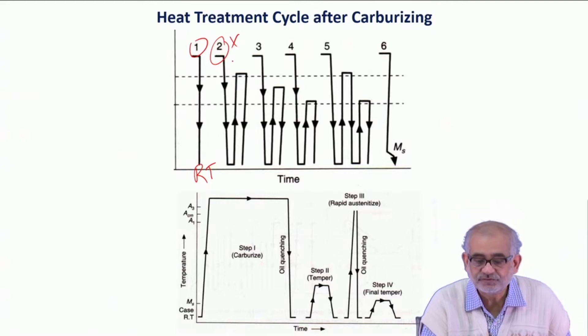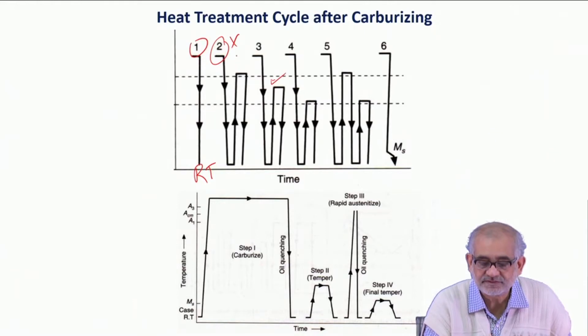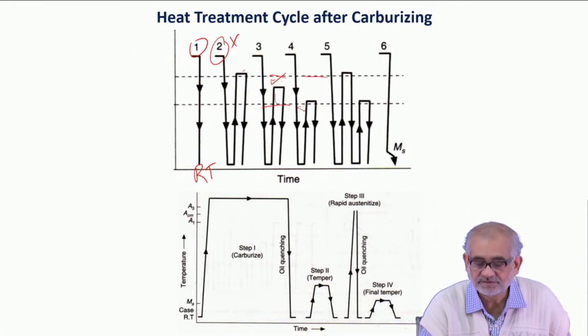So if we do separately, we might heat the surface to much higher temperature and then do a similar hardening treatment for the surface, which could be either between AC1 and AC3, or just above AC1, and when we quench in all cases we are actually quenching sharply so that we come to room temperature drastically.